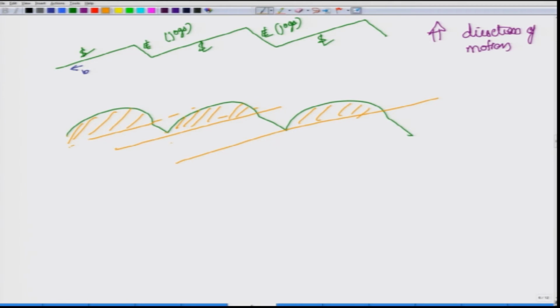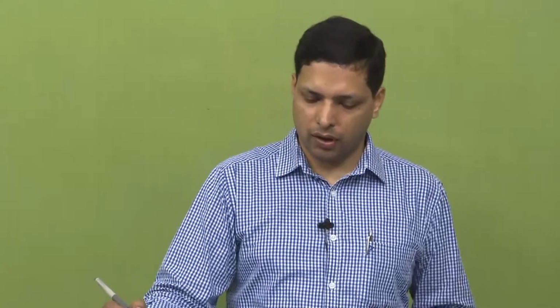And let us say you are applying thermal agitation and sufficient stress, then the sessile dislocation would also move upward along with the dislocation, but at the same time it will be leaving behind a trail of vacancies. You remember that whenever a climb of edge dislocation takes place, it leaves behind vacancies. There must be vacancies getting formed over here.